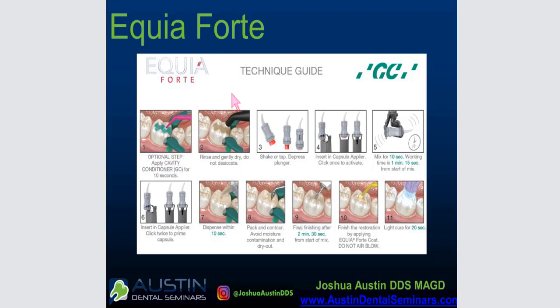I've always found this interesting, the optional step of the GC cavity conditioner, which is, if you remember from biomaterials, polyacrylic acid. The interesting thing about polyacrylic acid is that there's not a ton of good literature that shows that it really makes a huge difference in our restorations. What polyacrylic acid does is it just sort of frees up some of the calcium ions in the dentin so that we get a better chelation between the glass ionomer and the dentin, and so we get, hopefully, a stronger bond.